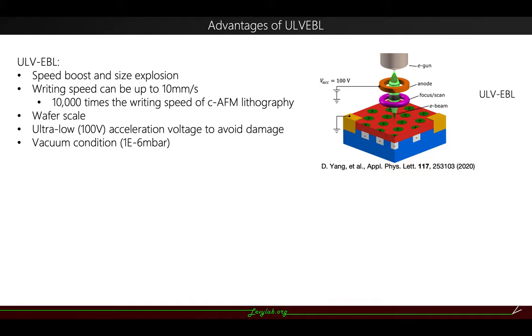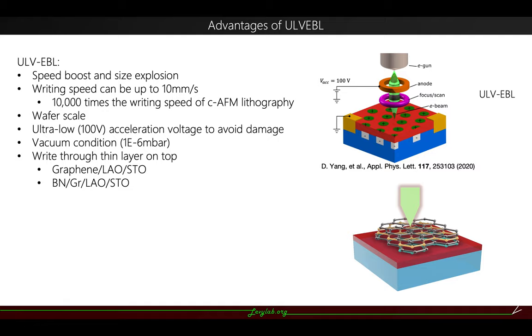to avoid damage to the oxide structures, to the sample itself. And the writing process is in vacuum. So the device itself will preserve during the vacuum, in the vacuum conditions. It will have a much longer lifetime.